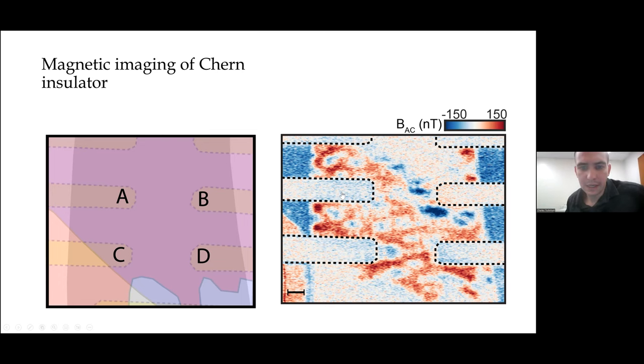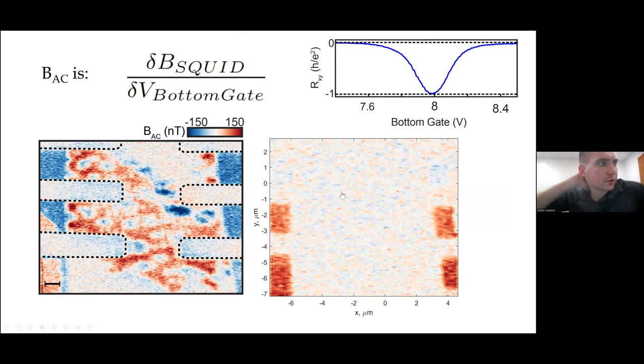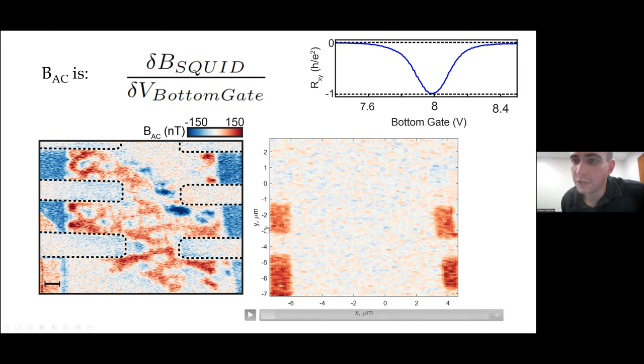So magnetic contrast is useful and has a lot of advantages over something like electrometry or STM. I discussed the fact that we can see through top gates earlier. One of the significant disadvantages is that it's non-local, right? Not only is the thing that we're imaging not precisely magnetic field, it's the derivative of magnetic field. It's also true that the magnetic field is not monotonic even in magnetization. So the local magnetic field is a pretty rich function of the distribution of magnetization around the sample.